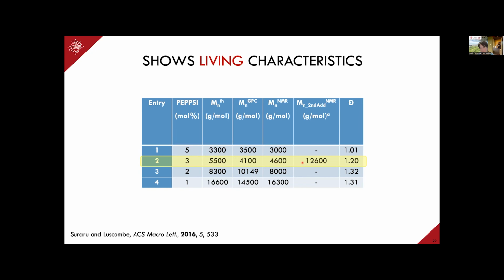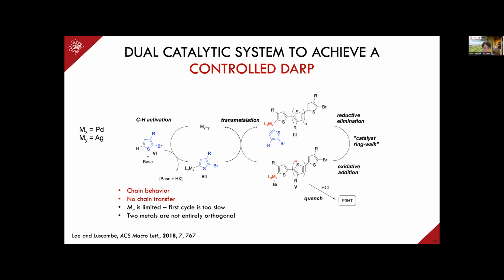called DARP. And we subsequently, after the gold work, we've optimized the system significantly. And what works best is now a combination of a silver catalyst and a palladium catalyst. And by doing so, we get a good polymerization.